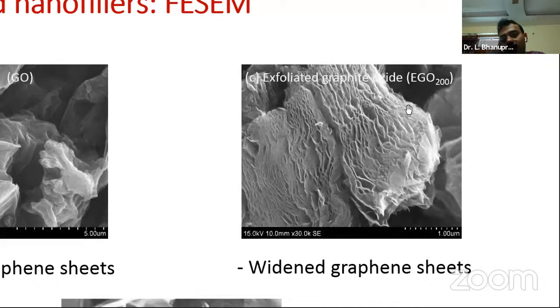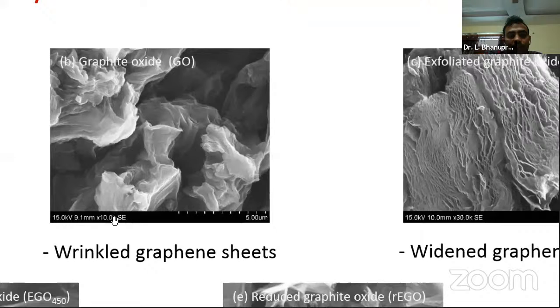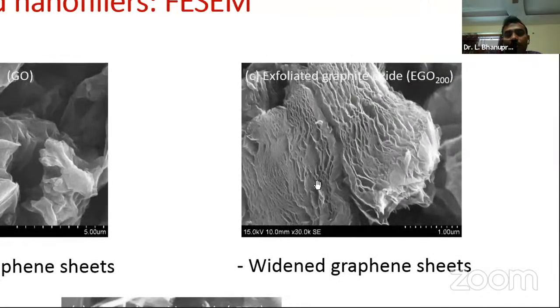If you consider this a stack of 100 sheets, maybe, or less than that, in each and every case I can say this is a single graphene sheet. Each graphene sheet is pushed away a bit because of the pressure being exerted. However, wherever possible it is also broken, and so the size of the graphene sheet in the exfoliated graphite oxide is further reduced. In the previous graphite oxide case it was observed at 10K magnification, but now to observe this exfoliated graphite oxide, I have to go deeper, to 30K magnification.